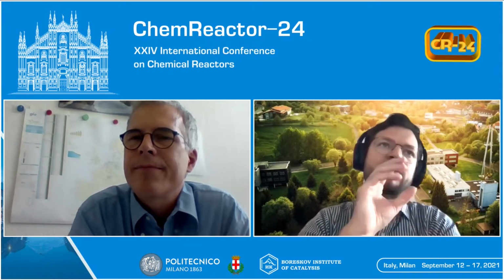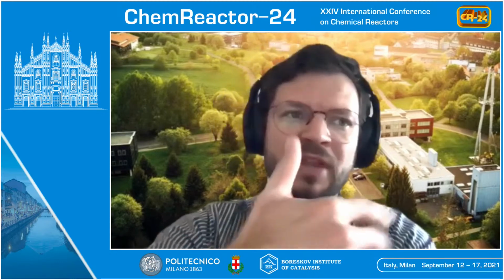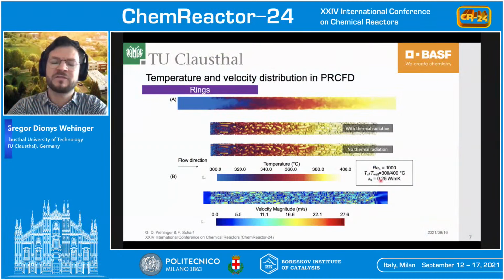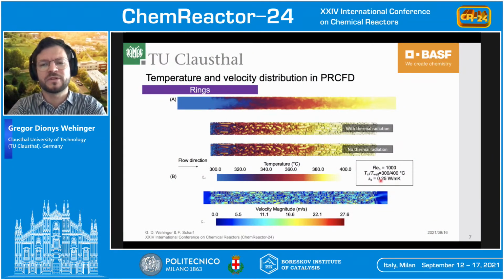Yes, I expect so. Because when we think of the different contributions of radiation, conduction, and convection to the overall heat transport, obviously if the thermal conductivity is lower, then thermal radiation is a larger driver. However, if the thermal conductivity is very high, for example, full metal particles, then probably this thermal radiation effect is a little bit minor. Here I used rather low values for the solid, 0.25 watt per meter Kelvin. So this is typically highly porous catalytic material. I also tested 2.5, and then the effect was a little bit lower than with this very low thermal conductivity. So yes, this is true.